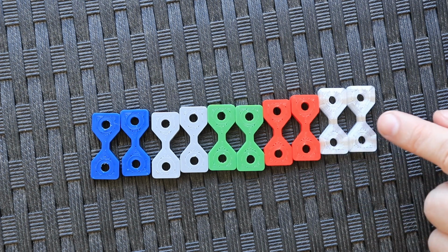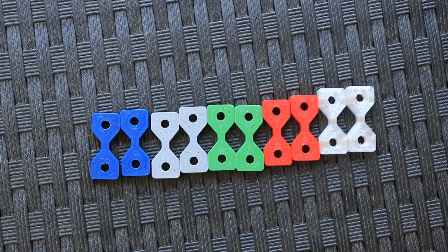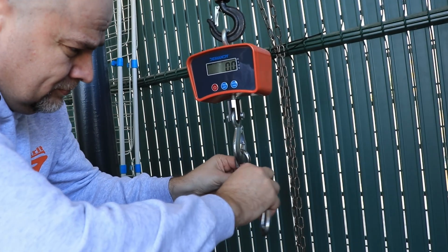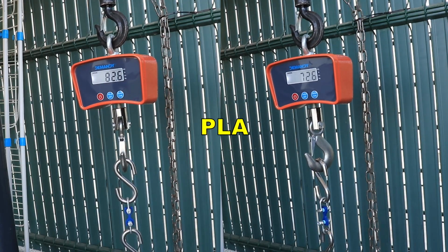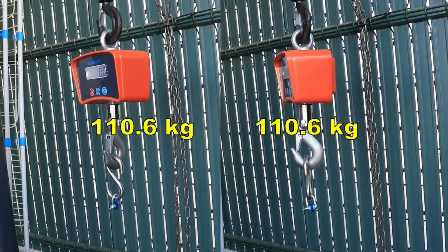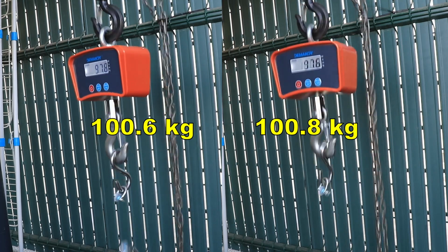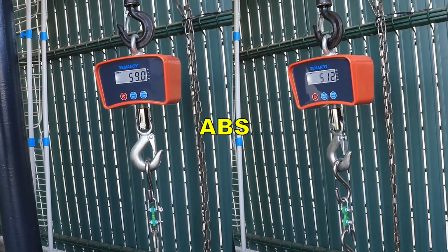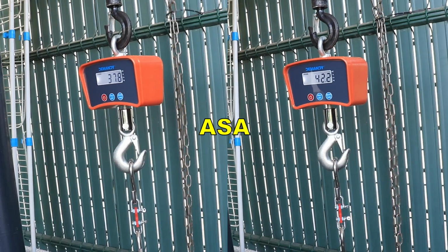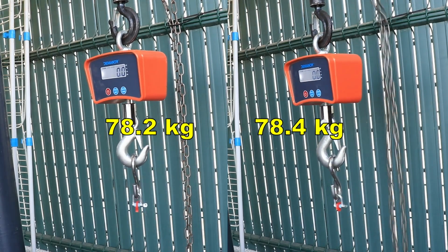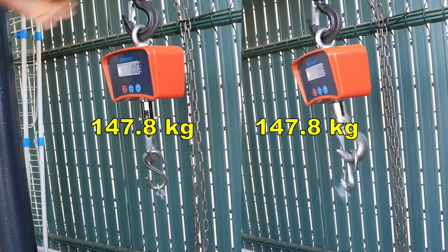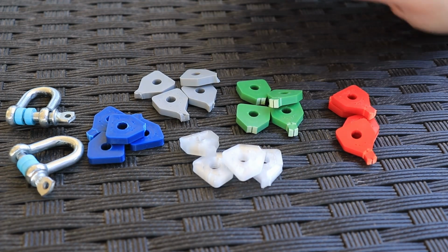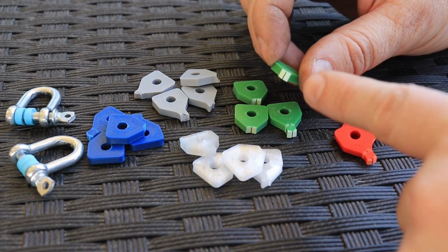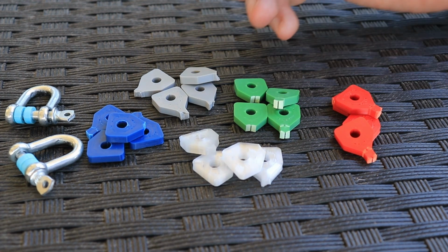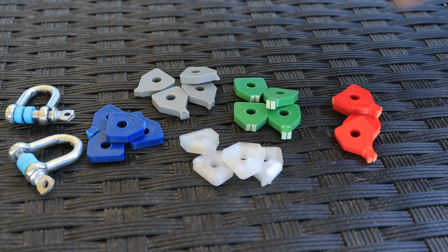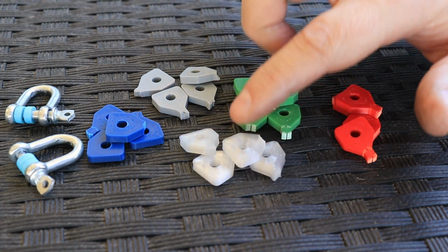The tensile strength test. These test specimens are printed in horizontal position. The smallest cross-section area is 4 by 4 millimeters. All objects broke on that smaller cross-section area. An interesting property I noticed with ABS is that before it breaks it always becomes white, and this property may be useful in some applications for safety reasons. And I don't know the numbers yet, but from the feeling, definitely the polycarbonate was the strongest.